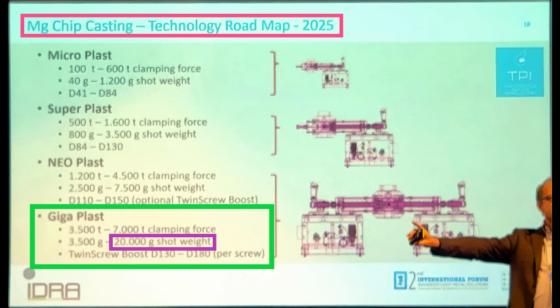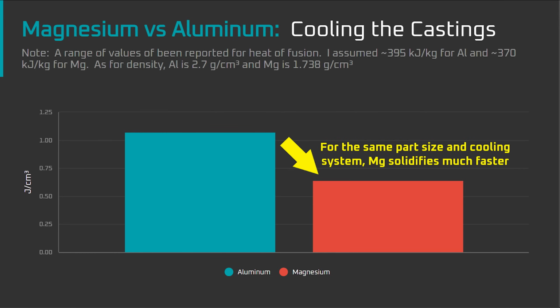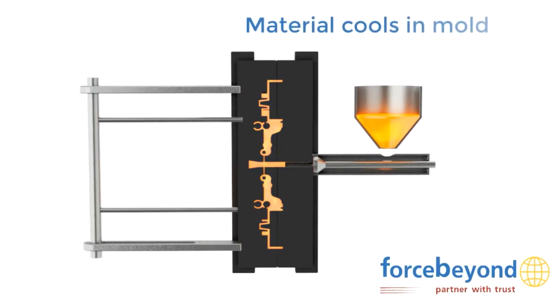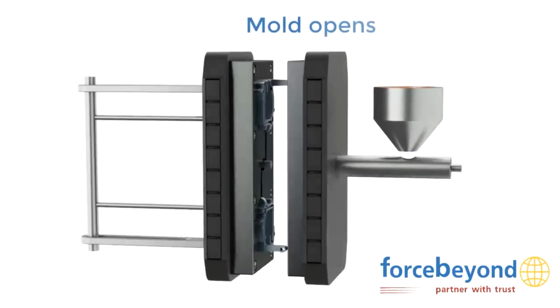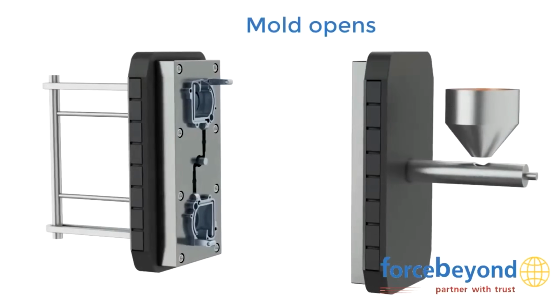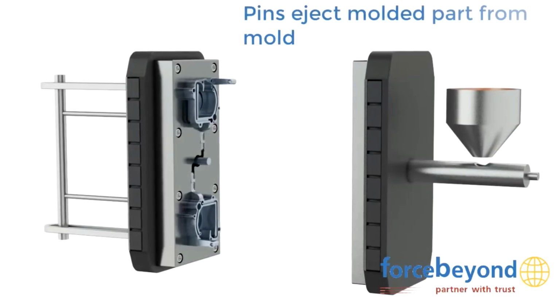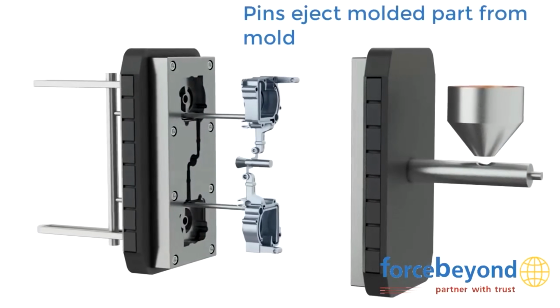In short, yes. First, with regards to production rate, magnesium has a lower heat of fusion and it's less dense than aluminum, which means for the same amount of cooling power and volume of material, magnesium solidifies more quickly. Additionally, molten magnesium is less reactive with the die, or metal mold of the gigacasting machine, which means that cast magnesium parts aren't as prone to sticking to the die and can be removed easily.